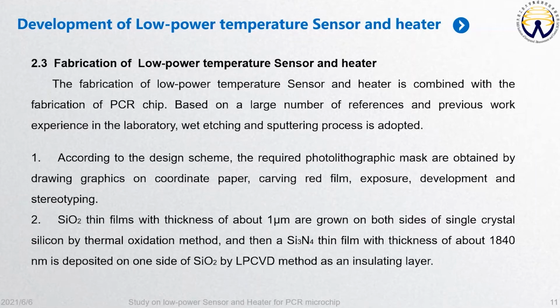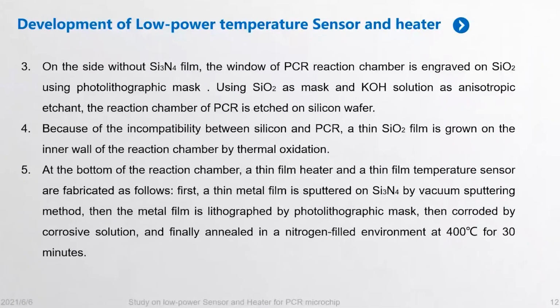the silicon dioxide thin film with thickness of about 1 micrometer is grown on both sides of single crystal silicon by thermal oxidation method. The third step is, on the side without silicon nitride film, the window of PCR reaction chamber is engraved on silicon using photolithographic mask.